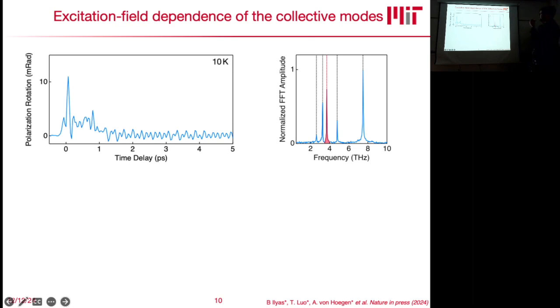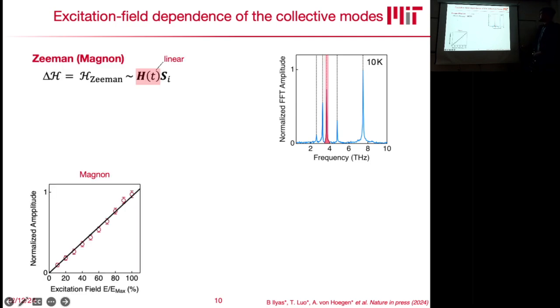So to actually get to know more about the nature of these modes, and if you also see these fingerprints of this hybridization between magnons and phonons, we now conducted more experiments at this low temperature. For one, we conducted an excitation field dependence. So we basically changed the strength of our excitation. And so what you would expect for the magnon, because the magnon is excited by magnetic dipole coupling. So the magnetic field component of your terahertz field couples to the magnetic dipole and linearly excites it. So it's basically like this linear excitation. This is exactly what we find, that the height of this peak linearly changes with the excitation field. So this is very much in line with this type of linear excitation.